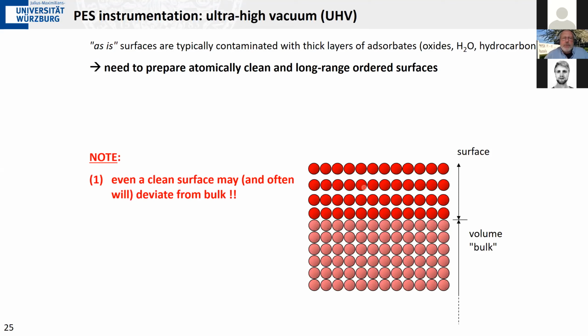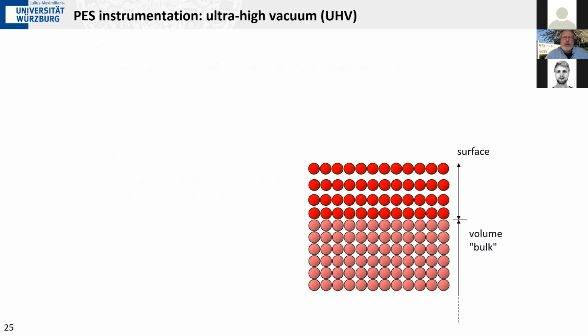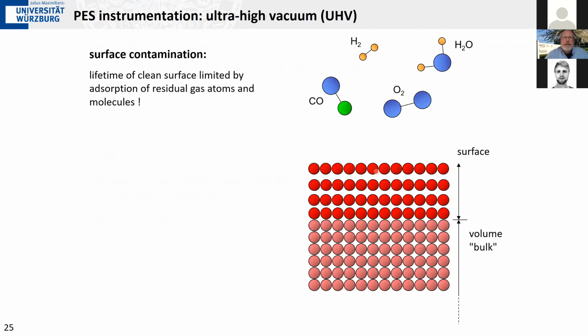So first of all, we have to keep in mind that even a clean surface may be different from the volume. What we want to study is mostly this volume, but even if I have a clean surface, there may be some changes. For example, here I have some surface relaxation that would affect the band structure, for example. And the clean surface that I have just prepared does not necessarily stay clean. And you can do a simple kinematic estimate how long it takes as function of pressure to keep the surface clean.